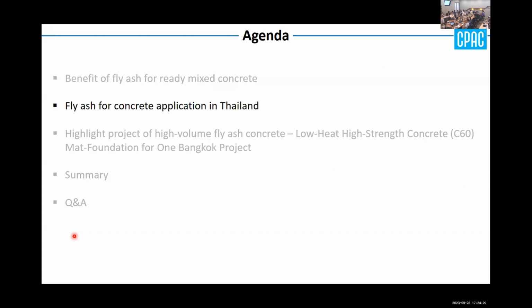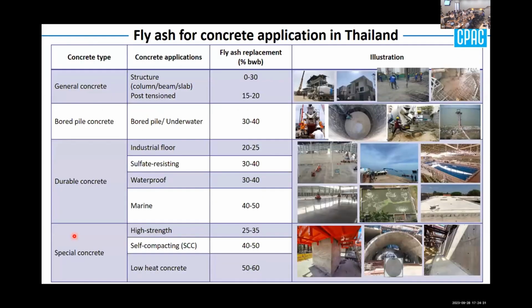I just want to give you some photos of applications in Thailand where we use fly ash for various concrete applications. For the concrete types here, you can see we use it for general structures, post tension. You can see the fly ash percent as replacement of cementitious material, starting from no fly ash up to 30% replacement of the cementitious material.